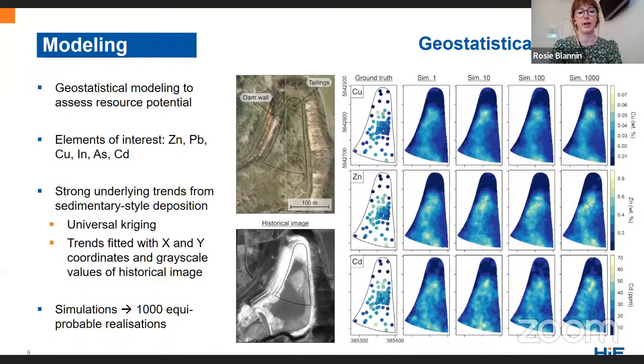And first we did this with the X and Y coordinates of the sample locations. So the kind of the correlation between the location and the composition. And we also did this with the grayscale values from a historical image. So the one on the bottom left of this figure, it was taken in 1967, so just after the deposition in the tailings ceased. And we found that if we extracted the grayscale values of the sample locations, it correlated very nicely with the composition. So we also decided to try and use this to fit the trend.